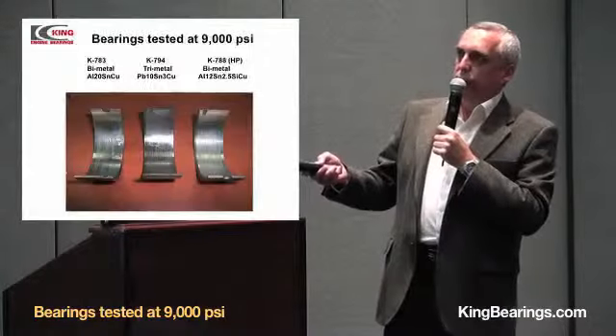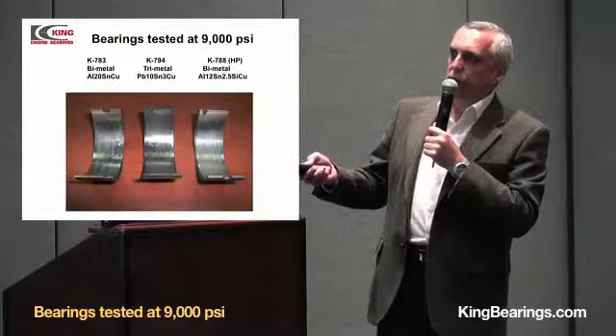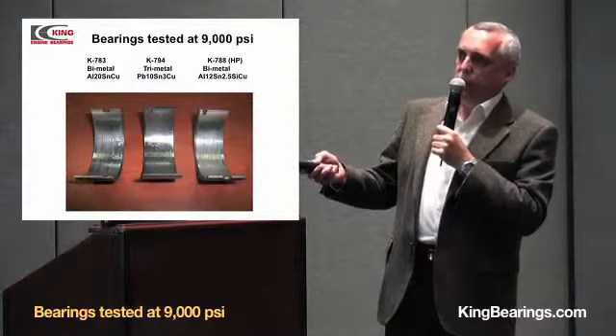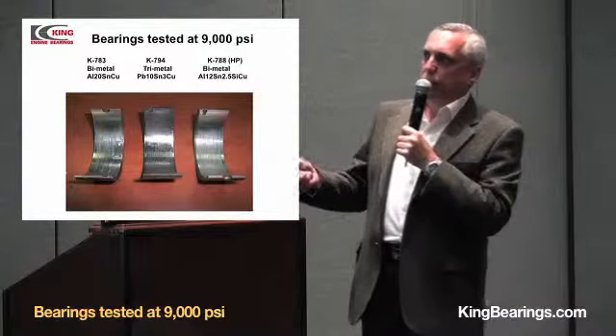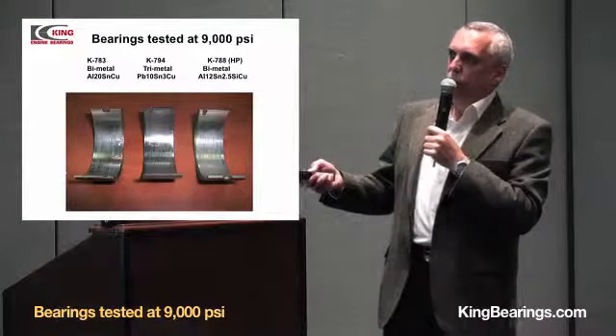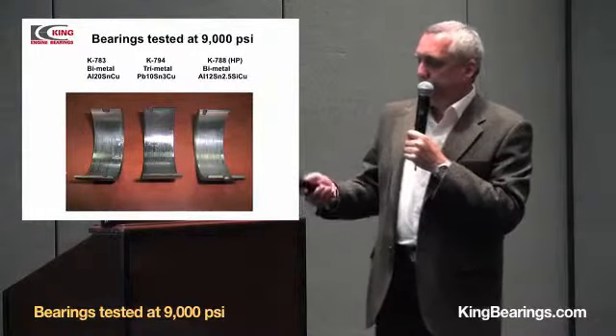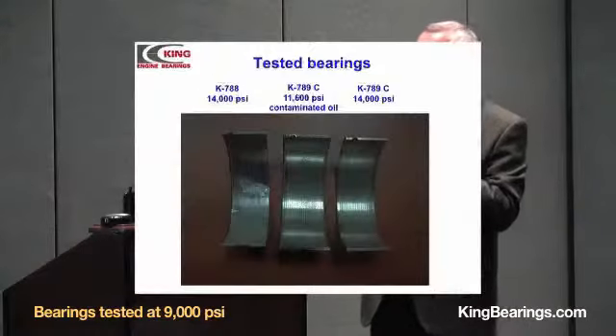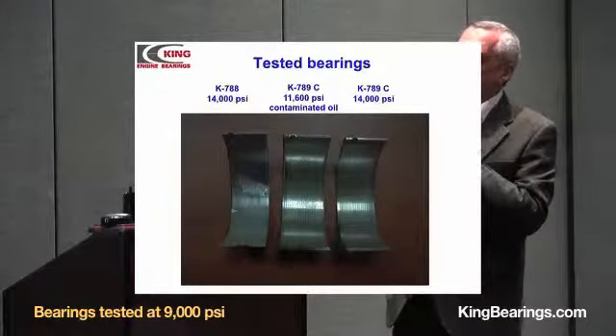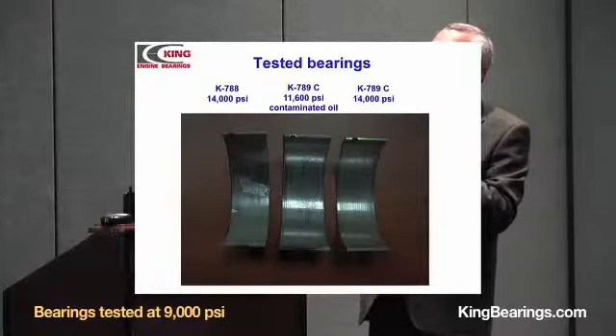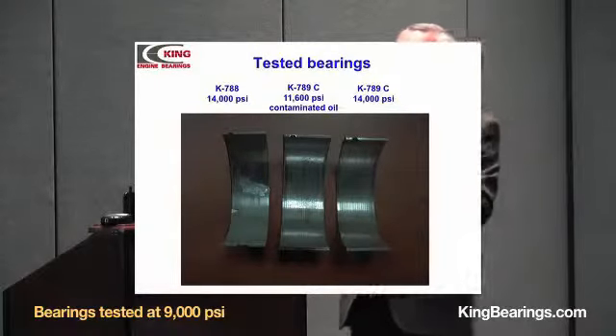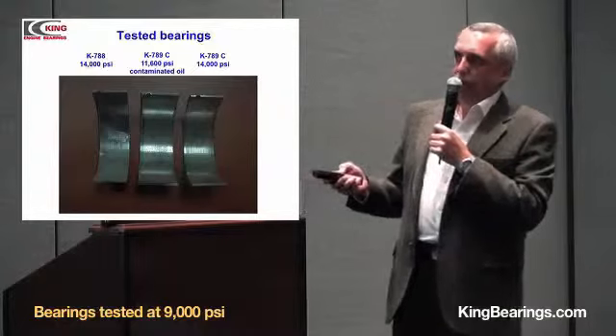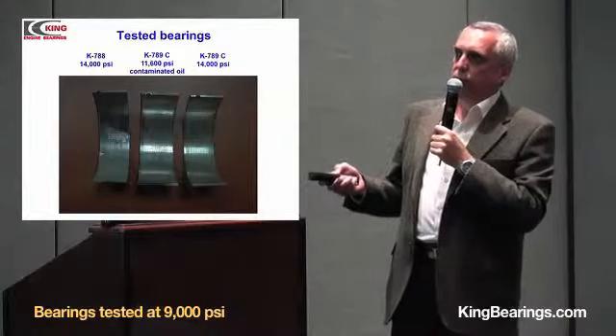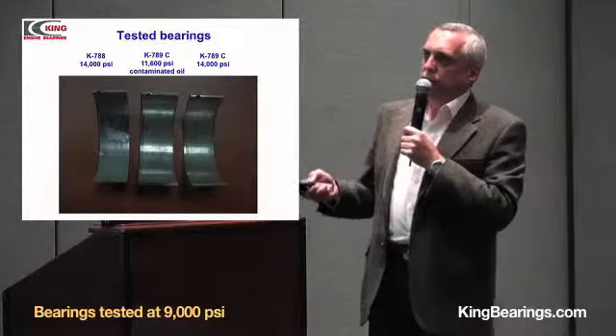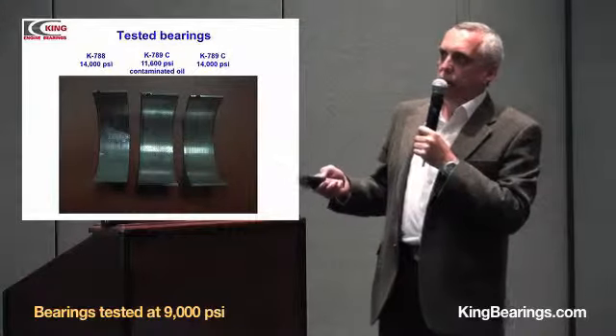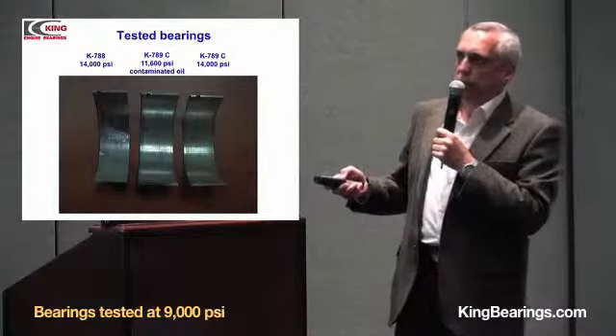For example, for this material, you see fatigue in this area. You see also fatigue cracks on the overlay of the trimetal material. You see this bearing with no fatigue signs. This is another example: fatigue on the aluminum surface. And these are two bearings made of high-strength aluminum. They were tested at very high load, but there is no fatigue. This bearing was tested with contaminated oil. You see the particles embedded in the aluminum surface.